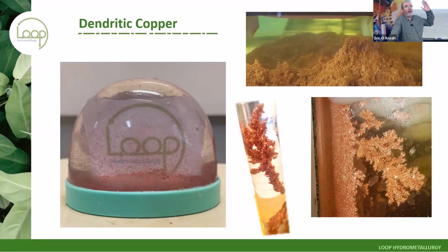You went from having a notional surface area of X amount of square meters, but with all that dendrite, your effective surface area was probably 2 to 3 orders of magnitude higher. So when you wiped the cathode, effectively your effective current density jumped by 2 to 3 orders of magnitude. Your voltage jumped. The morphology of the product that you produced in the minutes afterwards went to hell, and so did your product purity because of the boundary layers around the much lower surface area.